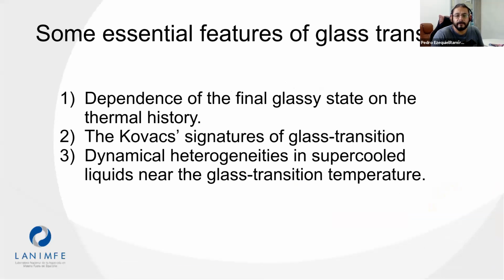The glass transition phenomena have an overwhelming literature and many points of view converge on the problem. However, many of the glass formers present a set of characteristics independently of the specific nature of their microscopic components. A short and for sure incomplete list of such essential features are the following. First, the dependence of the final glass state on the thermal history, the Kovacs signatures of glass transition, and finally, the dynamical heterogeneities in supercooled liquids near the glass transition temperature. These issues form a sort of checklist for any theoretical approach to the glass transition problem.